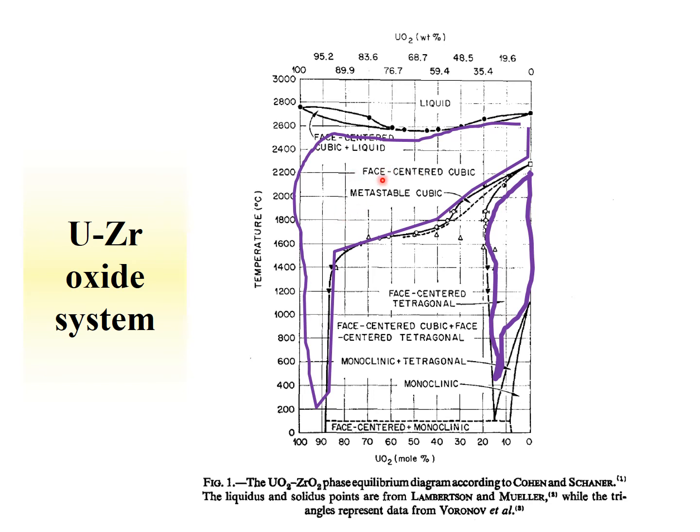Over here we'd have face-centered cubic structure dominating in this area. When we got to higher and higher amounts of zirconium, obviously more than you would see in nuclear fuel, you would have the face-centered tetragonal form dominating. You'd have a mixed phase here and then a monoclinic form here. Within this regime, at lower temperatures, we have two species formed.